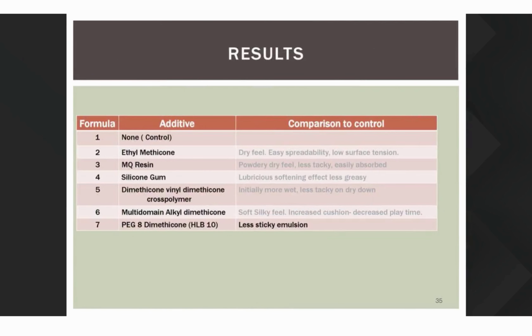Finally, when we go back and look at the emulsifier, because it has more silicone in it, it's going to be less sticky in the emulsion. It also, if you remember, we lowered the viscosity of this product, so we'd have to go back and correct the viscosity. Since we were primarily interested in the other aspects of this formula when we did it, we never really did a lot of work with changing that, but there's a lot of things that you can do to get the viscosity back, or perhaps you may not even want that high viscosity if you want something that can be sprayed.